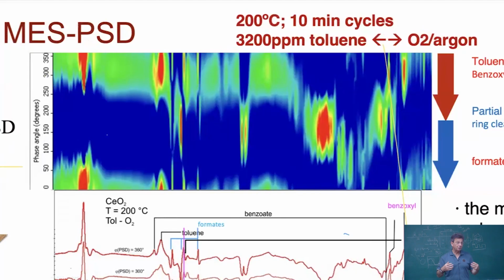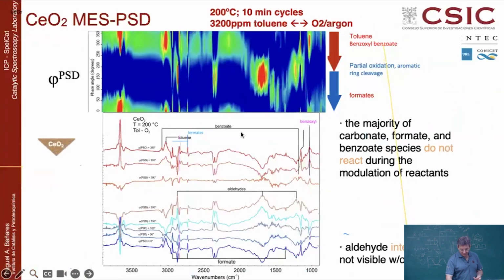So they are in phase, which probably means that either two molecules happen at the same time, or very likely it is one molecule which is going through a maximum at that moment, or bands that are being consumed at the same moment, like this, or this, and this is decreasing. So you can always tell things apart at a given moment in time. And then, because of the MCR analysis, you can also identify who is being formed and who is being destroyed, and then you can see a number of components from this spectrum, like if you cut here or here or here, and you make just a plot of selected moments of the phase, selected angles of the phase. For instance, here you get 360, 300, 250, 200 degrees of angle of the phase.